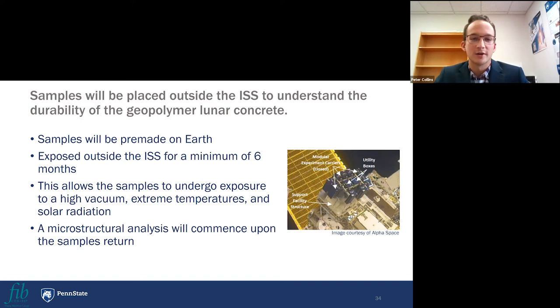And so these will be pre-made on Earth. They'll be placed into the blue carrier trays that you see on the right side. And they will be shipped to the ISS and placed outside. And then the cover of the carrier will come off and they'll be exposed to the extreme environment. And this will really allow these geopolymer lunar concretes to undergo exposure to the high vacuum environment, as well as extreme temperatures and solar radiation. Concurrently with that, we will leave just normal samples here in a laboratory environment to have as a control and basis for when the samples return. They should be exposed outside the ISS for a minimum of 6 months before they start to return. Once they do, we'll do our microstructural analysis.